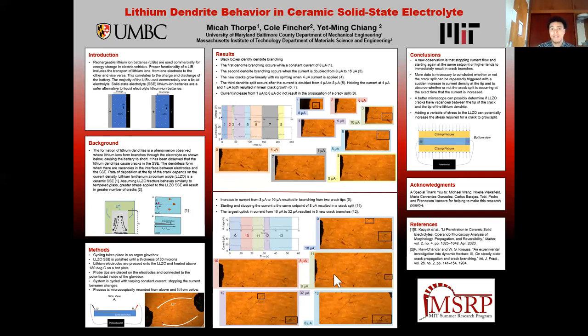In figure 11, after we stopped flowing 8 microamps and then started again at 8 microamps, we saw a 2 split pictured here. And then we stopped to increase our current to 32 microamps, our largest jump. In the bottom right corner, you see a split of at least 5 lithium dendrites that form when we jump to 32 microamps. And then we see a 2 split at the top. It can be further seen in figure 13 as dendrites grow at a lower current.